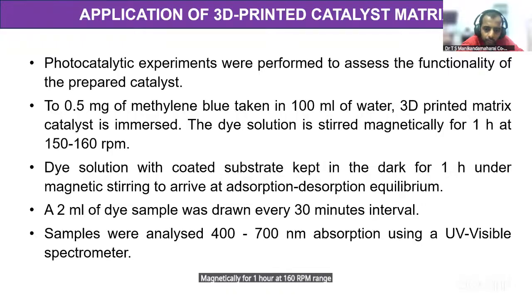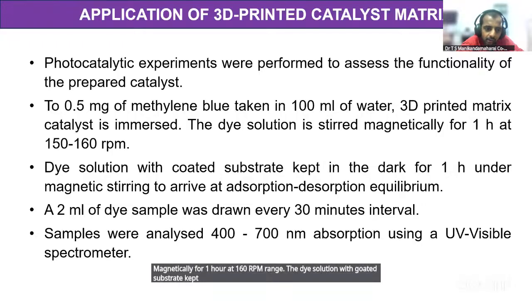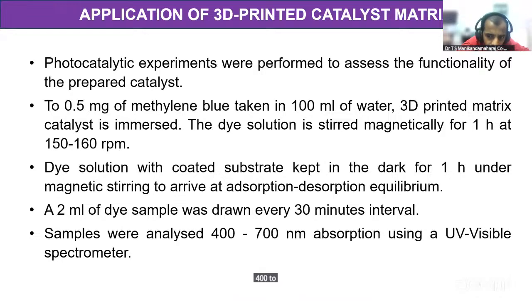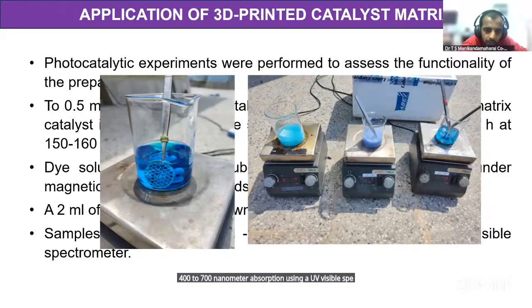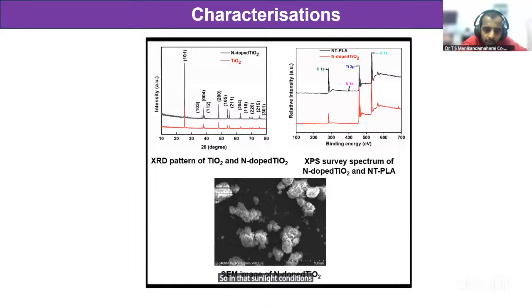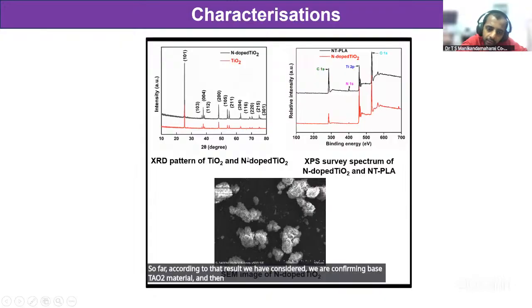The dye solution with the coated substrate is kept in the dark for 1 hour with magnetic stirring to arrive at adsorption-desorption equilibrium. A 2 ml dye sample was drawn every 30 minutes. The sample was analyzed for absorption from 400 to 700 nanometers using a UV visible spectrometer. So in sunlight conditions, according to the results, we are confirming the base TiO2 material and then the N-TiO2 material, confirming the synthesized N-TiO2 presence in XRD, XPS, and the images.